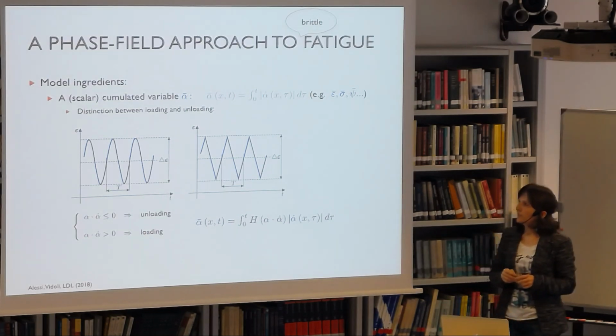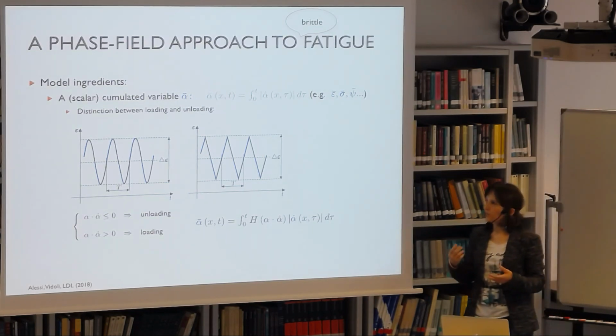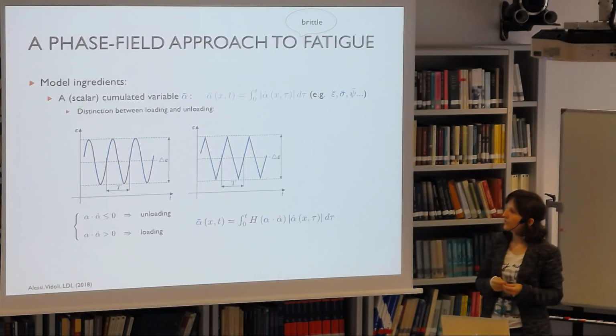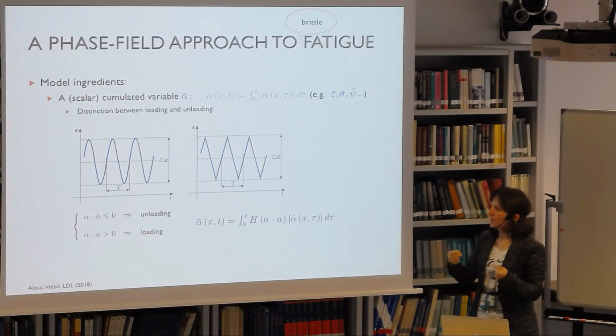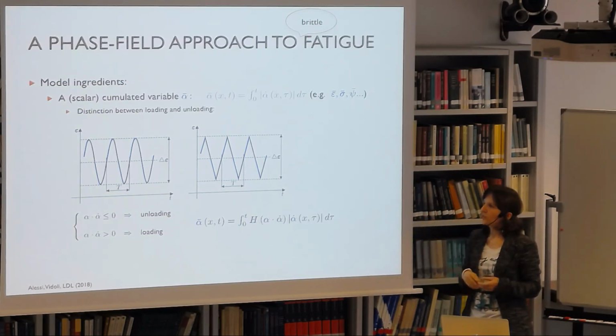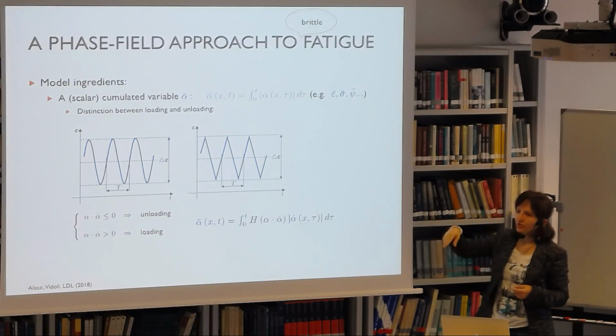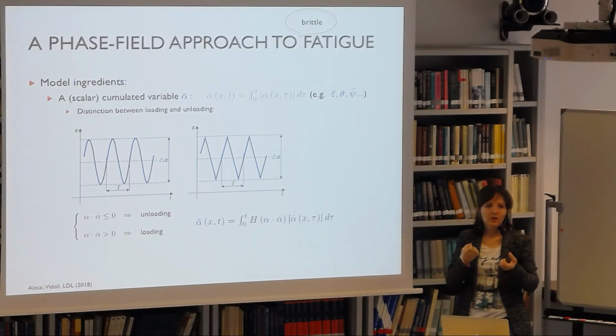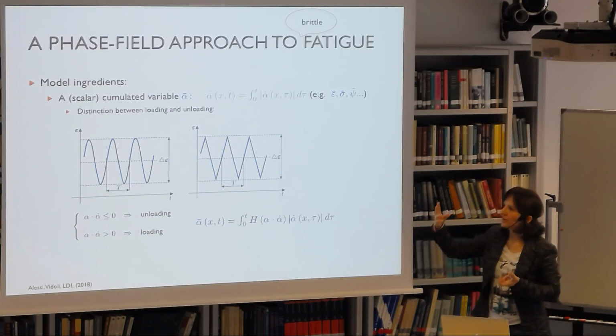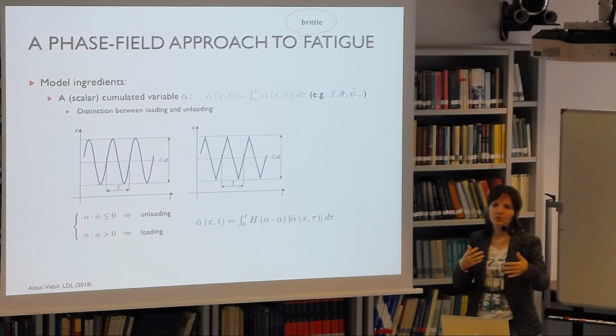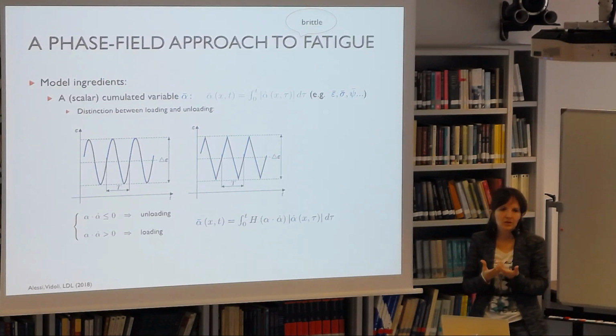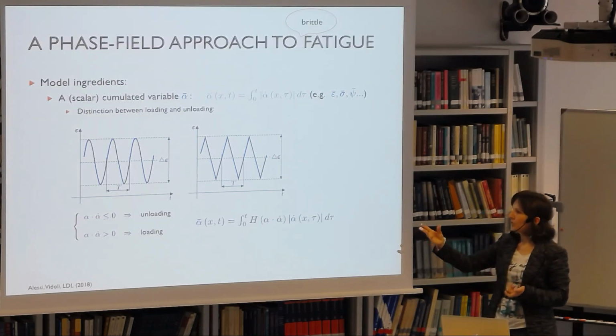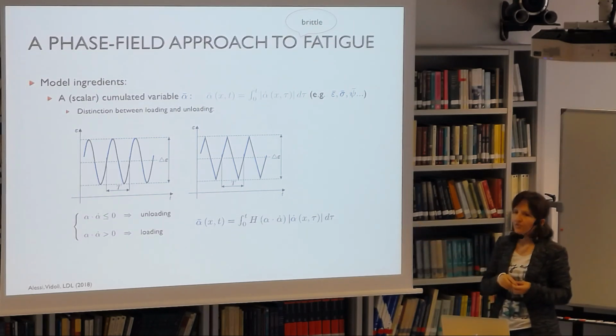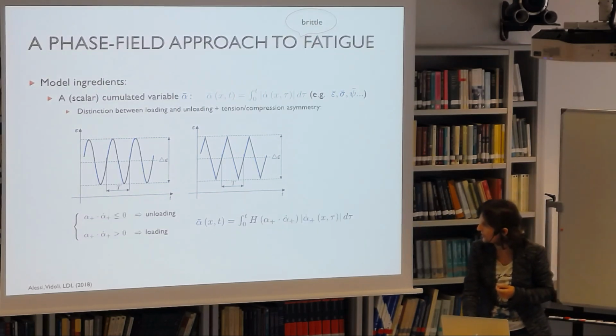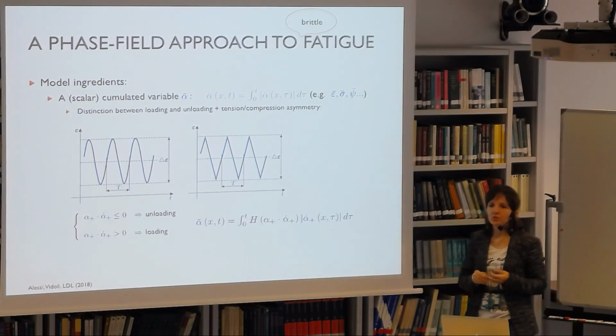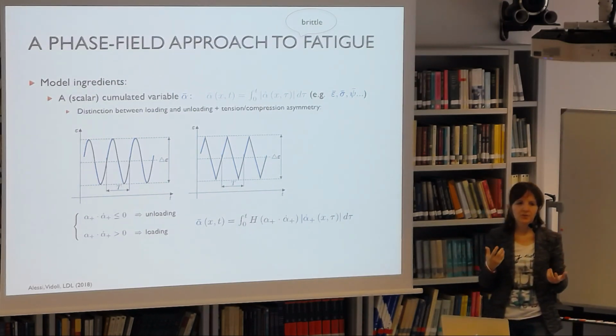Then we also want a distinction between loading and unloading. So if you consider an easy one-dimensional situation where you have an epsilon, one-dimensional strain that is varying sinusoidally over time, you want only the blue portions of the history to accumulate your fatigue variable, because those are the loading phases, and many experiments have shown during unloading the fatigue effect is not there. So you need some condition for accumulating your variable only during the loading phases, and possibly you want to account for this tension compression asymmetry that I was mentioning before.